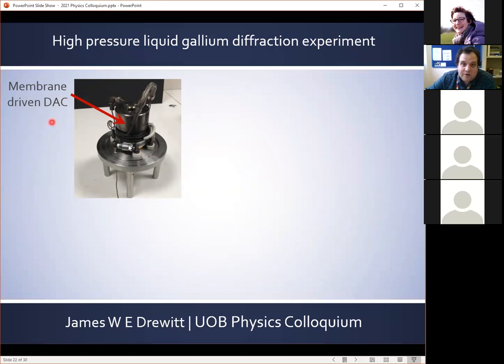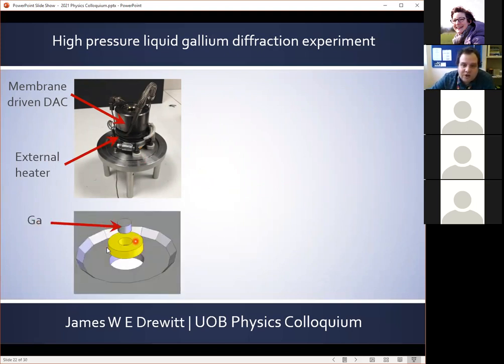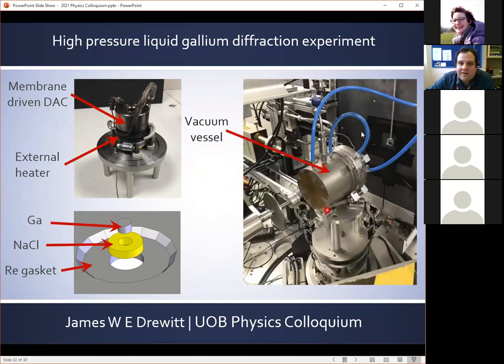And so we used a membrane-driven diamond anvil cell equipped with an external heater. So the whole diamond anvil cell heats up, and our gallium sample is placed within a sodium chloride ring in order to isolate it from the rhenium metal gasket. And then the whole diamond anvil cell assembly is placed within a vacuum vessel at beamline I15 at the Diamond Light Source, and we have a highly focused X-ray beam incident through our liquid sample, and we measure the liquid diffraction pattern as a function of pressure.